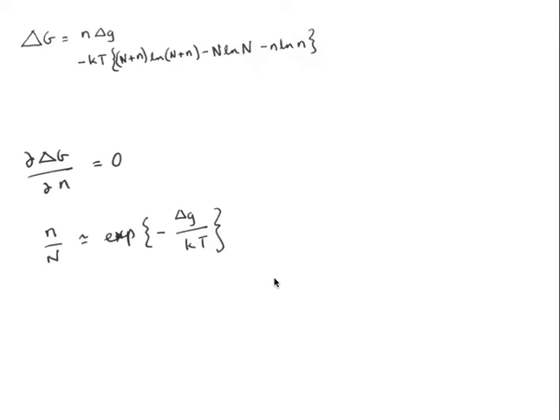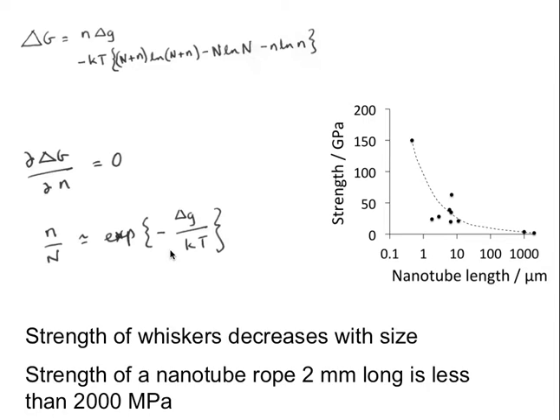What was forgotten was elementary thermodynamics - this is part 1A diffusion stuff. When you create a defect, there's a cost opposing its formation. But you increase the number of configurations, reducing free energy. These terms balance out, giving an equilibrium number of defects. Nothing you can do about it - it's a thermodynamic principle.